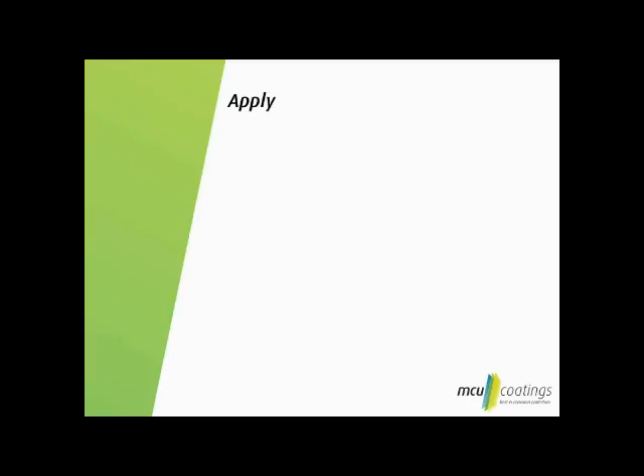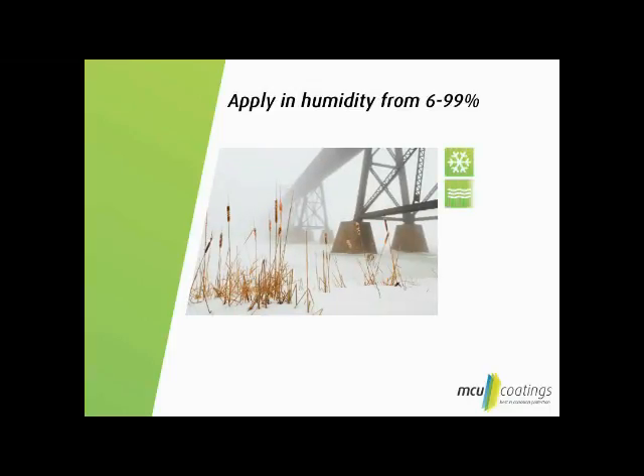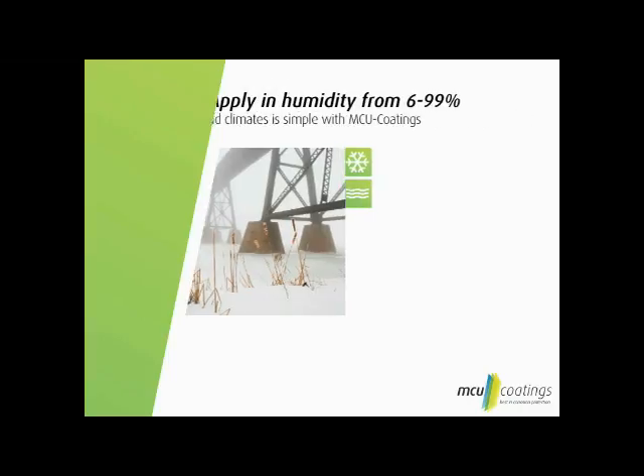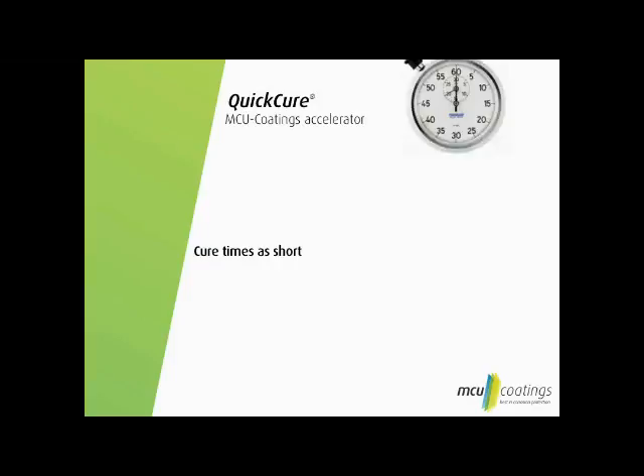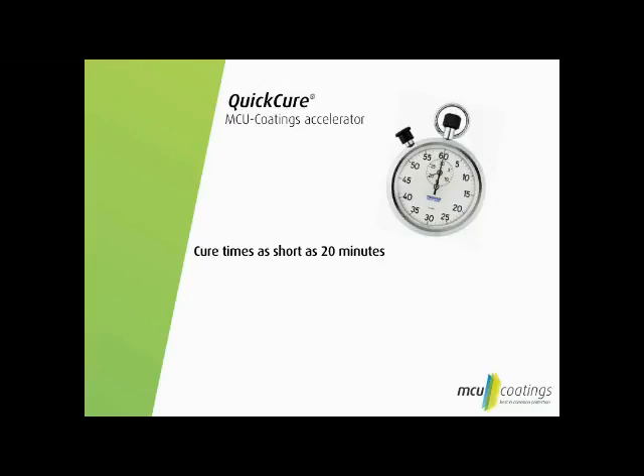MCU coatings can be applied in humidities of 6 to 99%. Plural component epoxies and urethane coatings cannot be applied above 80 to 85% relative humidity. Painting in high humidity tropical areas or foggy cold climates is simple with MCU coatings. With MCU Coatings' Quick Cure Accelerator, cure times between coats are as short as 20 minutes. With Quick Cure, a 3-coat system can be applied in as little as 2 hours.